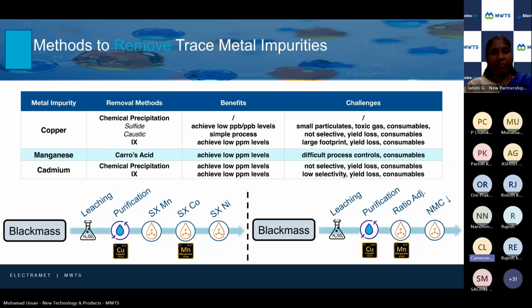You can add some sodium hydroxide as a base to precipitate out iron and aluminum and maybe 90% of the copper. But that's still not enough. So typically what they would do then is sulfide precipitation or ion exchange to try to get it all out. This results in significant yield loss, which erodes your economic viability as a business.